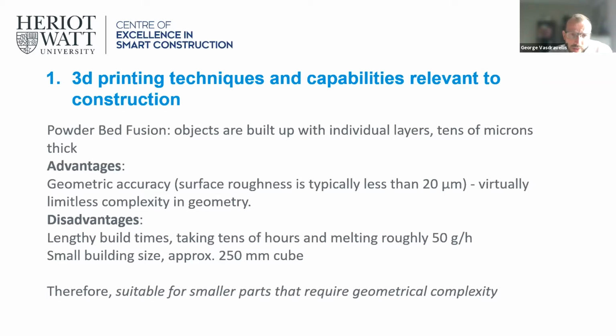The disadvantage: there are two major disadvantages using this technique. One is that the build times can be very long, taking tens of hours or even days. The melting rate is roughly 50 grams per hour. The other major disadvantage is that the size is limited by the chamber used in the machine, which currently is approximately 250 millimeters by 250 by 250, so a cube. I think recently there are some machines developed that allow up to 500. But again, there is a limit in the size. Therefore, this technique is suitable for smaller parts that require geometrical complexity.